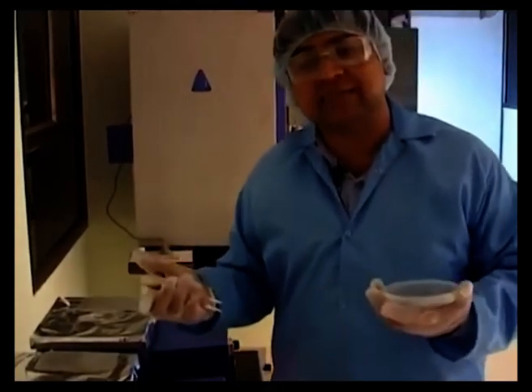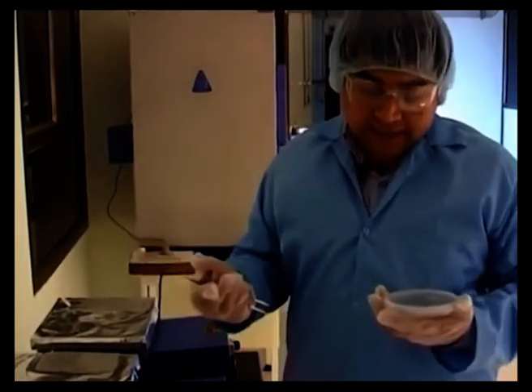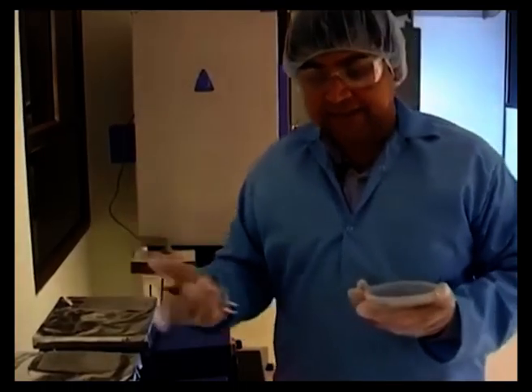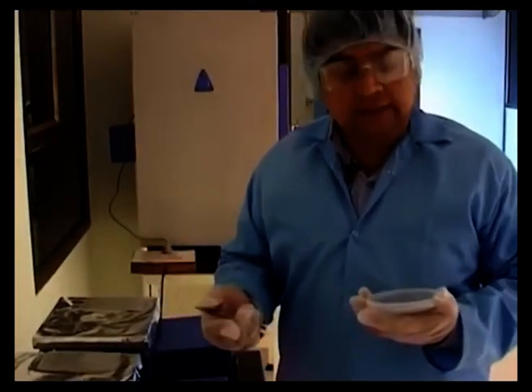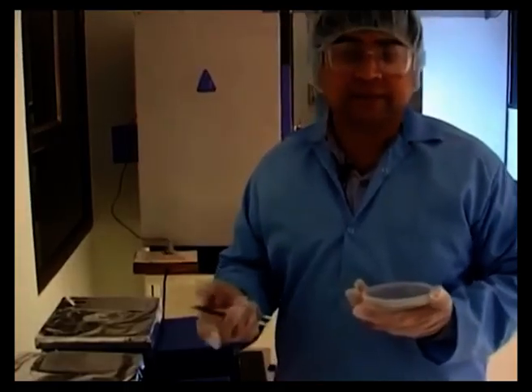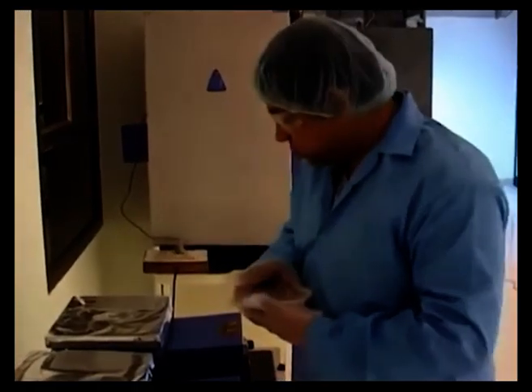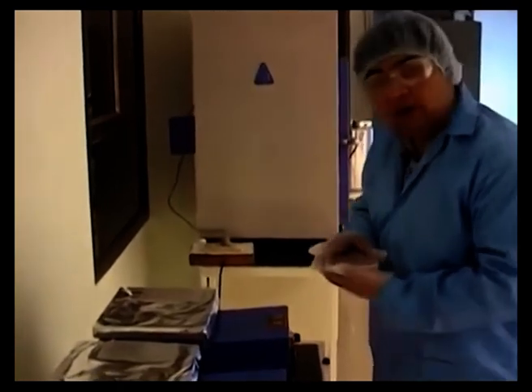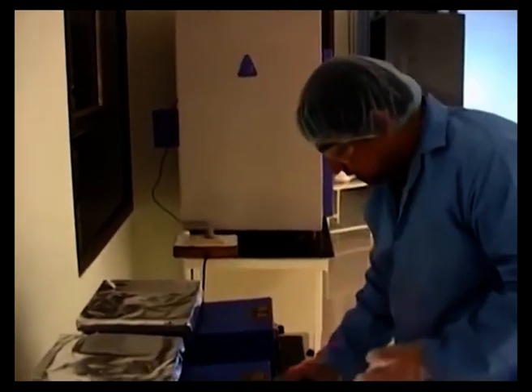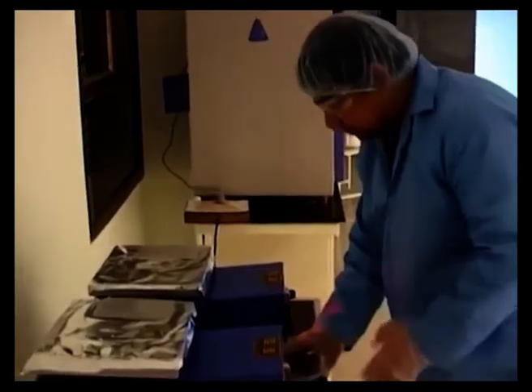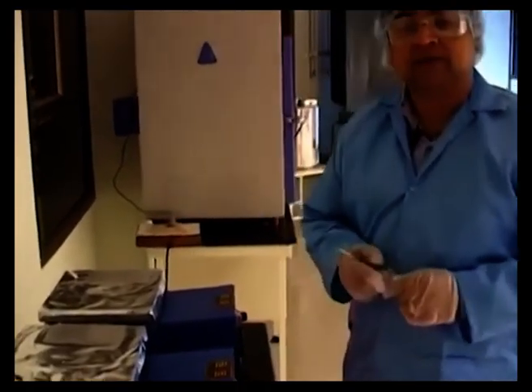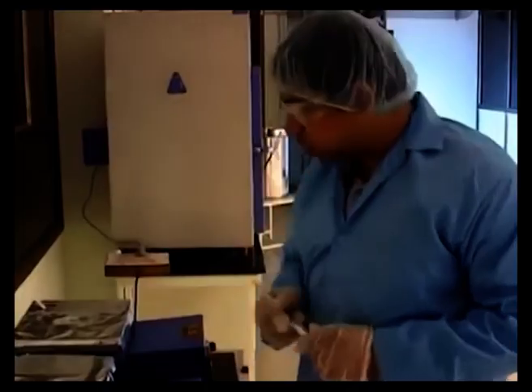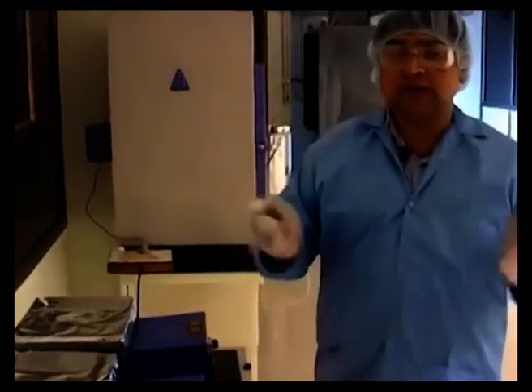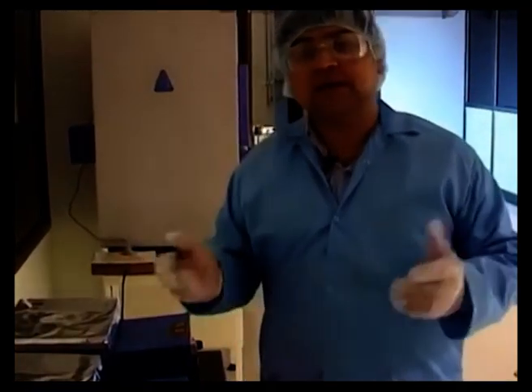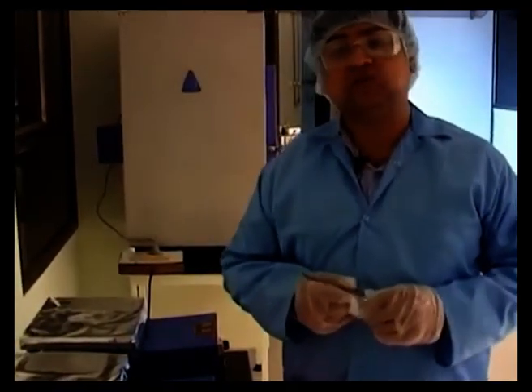We plan to actually do these things typically in clean rooms where the particle contamination may be as low as about close to Class 1000 or Class 100, depending on what kind of feature sizes you are using. So essentially we will hold this for some 5-6 minutes till it equilibrates back to the room temperature, and then we will actually use the second heating step of 95 degrees and put this resist back again for about 5 to 6 minutes for the full curing action to take place, after which we will do the UV exposure of the resist using the mask.